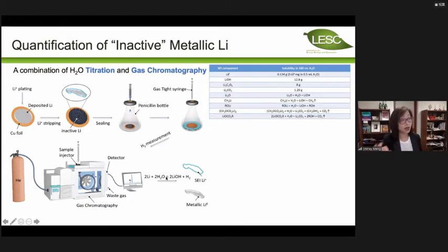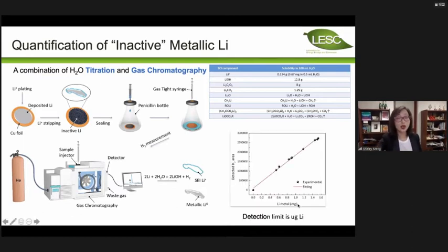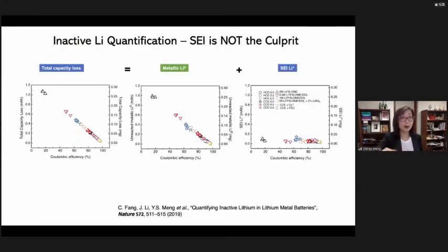So we only need to measure the hydrogen amount. When we measure the hydrogen amount, we found a very interesting phenomenon that agrees with our hypothesis: all the capacity loss is perfectly correlated with the metallic part of the lithium, not with the SEI. I want to emphasize that some of these Coulombic efficiency numbers are so bad because we deliberately chose an electrolyte that gave very bad Coulombic efficiency to prove the point.